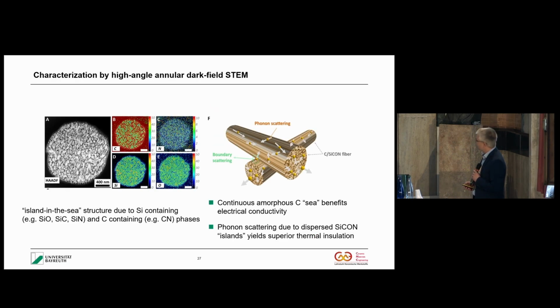And the reason actually is, again, the microstructure. So we used STEM, and we found out actually that we have a so-called continuous amorphous carbon phase, and we then have dispersed silicon carbon oxide nitride islands. They call it islands in the papers, or we called it islands, but I'm not so convinced. I would call it nano-composites. And that's the reason actually we have a lot of phonon scattering. That's the theory at the moment. And that's why we have this low thermal conductivity.